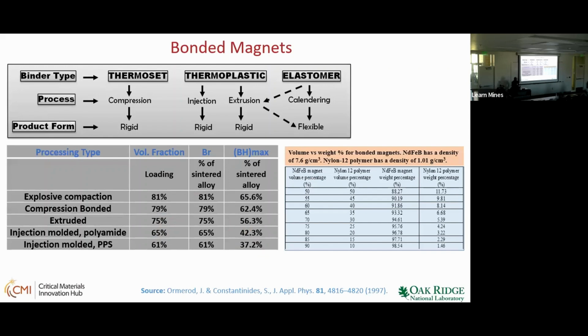So one thing I want to talk about is volume versus weight percent. There is a huge density difference between a polymer and a magnet. The magnet is a heavy metal, 7.6 grams per cubic centimeter, whereas polymer is close to 1. So you are mixing two very different densities for making a bonded magnet. So when I say 80 volume percent, here we are talking 96.78 weight percent. So almost 97 grams of magnet. If you take 100 grams of magnet composite, you have 3 grams of nylon polymer and 97 grams of magnet. So that's where, when I say volume versus weight, sometimes people get confused.